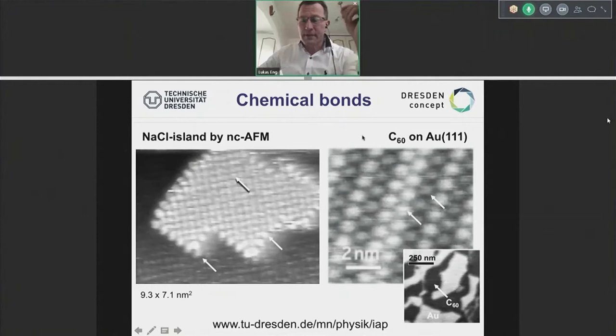Second example, on the right, C60 on gold 111, measured by Christoph Lobacher with us in Dresden with the big mammoth machine. And what we see here is that the C60 on the gold forms islands. And these islands, if you zoom in, have a fancy structure where you see two single bright C60 molecules, and you see one dark C60 molecule, and then again bright and dark.